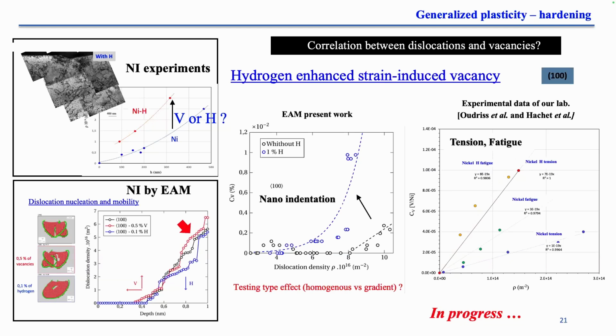And we can also correlate the effect of density of dislocation and the addition of hydrogen, which means that if you have no hydrogen, the concentration of vacancy for that one as a function of density of dislocation. When we add hydrogen, we have a large increase of the production of vacancy during the deformation. And this result is well correlated with the experimental data.